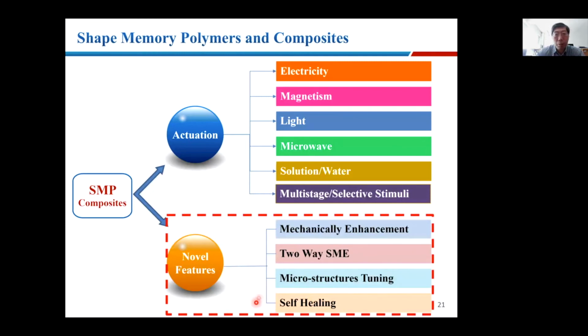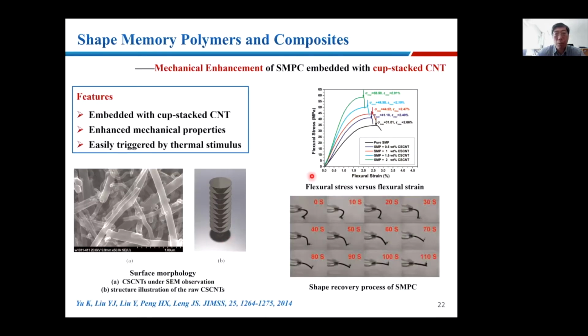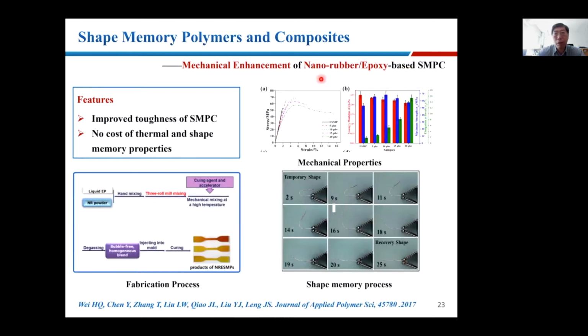Because, as I mentioned, we can also do some mechanical enhancement and two-way shape memory effect with different particles. This is one example. We make some cup-stacked carbon nanotube like this one, and we embed it in shape memory polymer. You can see this can improve the mechanical properties, including flexural stress, and this can also deploy when you apply the heating source. We also embedded some nano rubber.